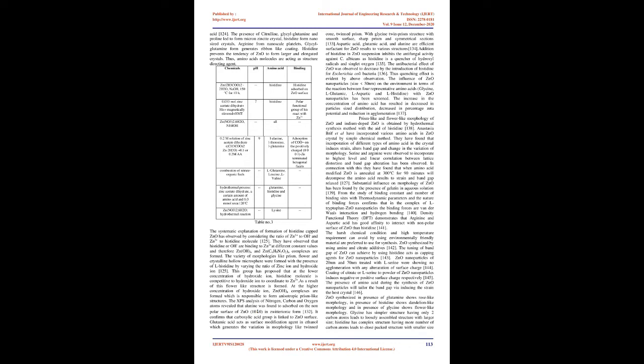XPS and temperature-programmed desorption, TPD, techniques are used to probe the adsorption of glycine on the rutile TiO2 (011) single crystal. The peaks of Ti 2p and O 1s were observed to attenuate by adsorption. Glycine was observed to form the zwitterionic H3N+CH2 with less stability, and the dissociated NH2CH2 structure with more stability, on the TiO2 surface 109. Glycine adsorbed on TiO2 surfaces like (110), (100), and (001) was monitored by glycine-modified AFM